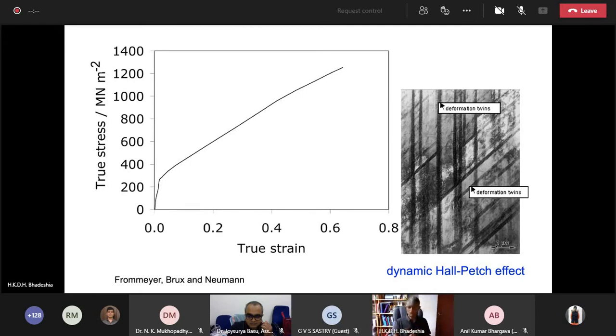I was talking about TWIP, twinning-induced plasticity steels, and the reason why we get this nice work hardening, which delays plastic instability, is that as you deform, you get mechanical twinning of the type illustrated here. And that mechanical twinning divides up the parent grains into ever smaller grains. So effectively, that gives you work hardening because you need to think about this like a dynamic Hall-Petch effect, where you're reducing the grain size by partitioning the grain with these mechanical twins. So on the face of it, it has excellent properties.